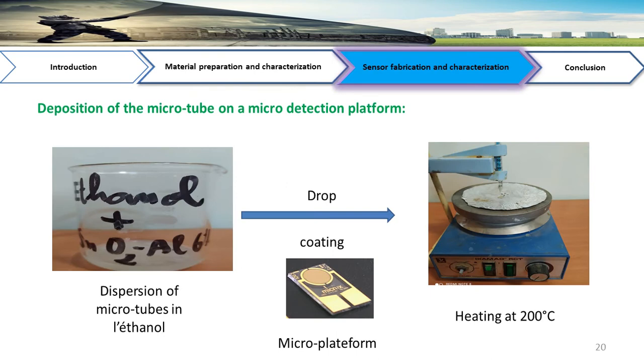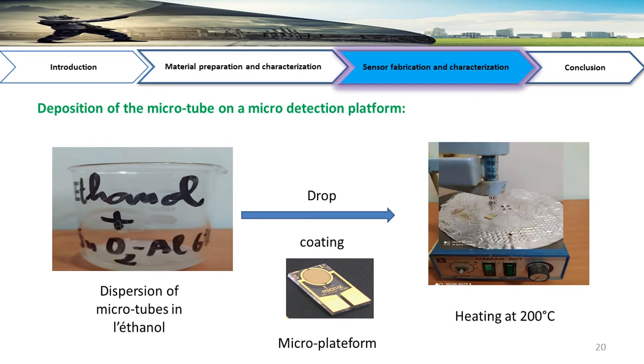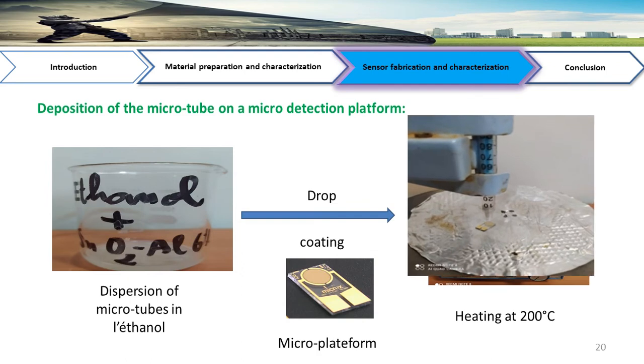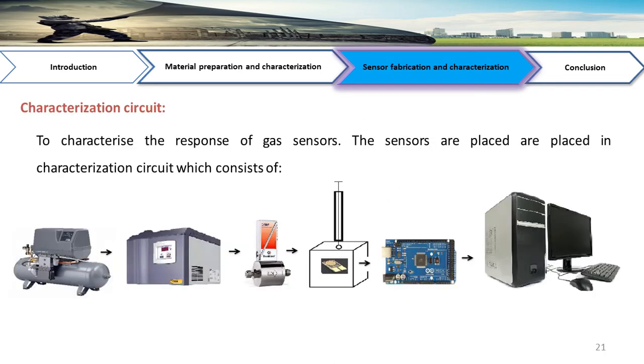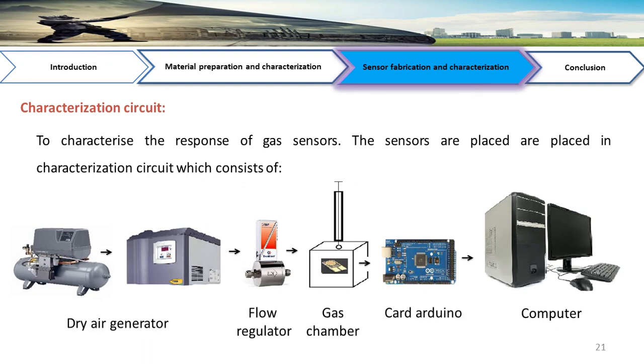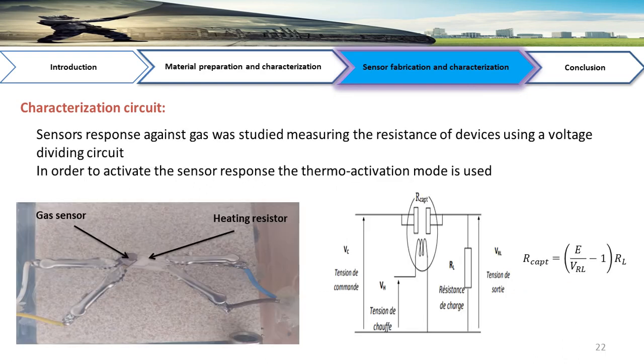To fabricate our sensors, we place the synthesized microtubes on a micro platform of detection with interdigitated gold electrodes separated by 10 micrometers. To characterize the response of the gas sensor, the sensors are placed in a characterization circuit, which consists of a dry air generator, flow regulator, gas chamber, Arduino card, controlled by a LabVIEW interface. Sensor response to gas was studied by measuring the resistance of the device using a voltage dividing circuit, and to activate the sensor response, the thermoactivation mode is used, as you can see in this picture.